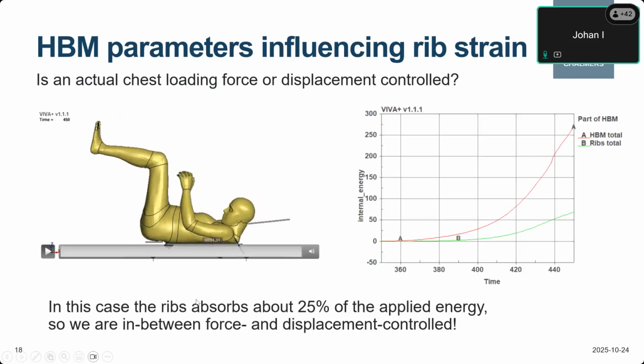So this means that we are somewhere in between force and displacement control. A pure displacement control would be if this energy in the ribs would be close to 0, and a pure force control would be if it's close to 100. But clearly here we are somewhere in between, but maybe closer to displacement control. And the reason for this is that we have a lot of other structures that will also carry load. So we have all the intestines, for example, and these are viscous, so the higher the loading rate, the more load they can carry.